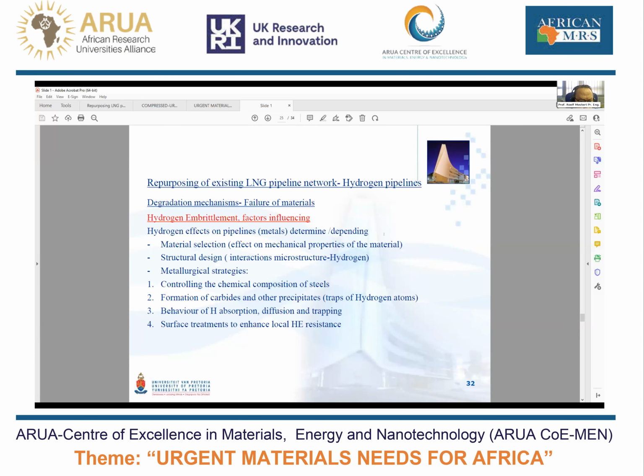So in terms of hydrogen embrittlement of pipeline materials, there are a number of factors influencing that. So the material selection, the specific alloy that has been selected for the pipeline, the structural design is quite important. And there are a number of metallurgical strategies that can be considered in optimizing the resistance to hydrogen embrittlement. The particular selection of the chemical composition, the formation of carbides and precipitates for traps, how the hydrogen is absorbed, diffused and trapped, and in particular surface treatments can also be considered to enhance local hydrogen embrittlement resistance.